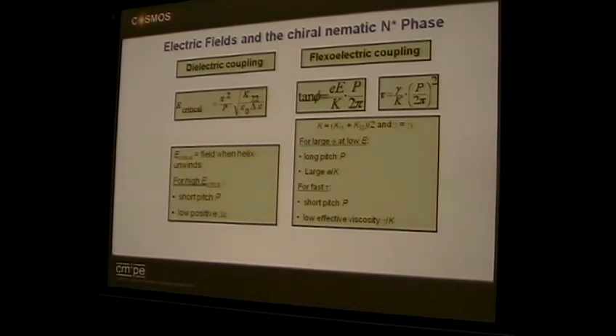A few key equations. If you apply too high a voltage, as I showed with the field, you unwind the helix, and you don't want to unwind the helix, you just want to see optical rotation. So you want a material with a high elastic constant, you can't change those too much, or low dielectric anisotropy. If you have a small delta epsilon, the critical field becomes very high.